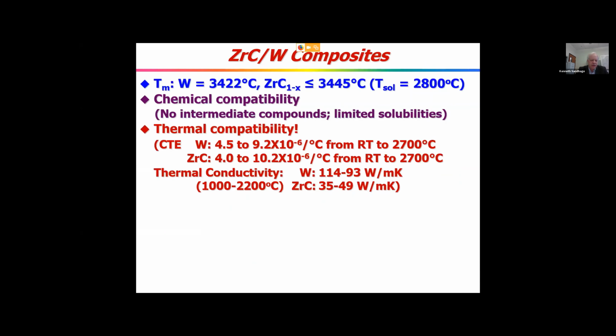What is particularly remarkable, and particularly why we picked this combination, is that they overcome an Achilles heel of ceramic-metal composites, and that's the difference in thermal expansion. The coefficients of thermal expansion between tungsten and zirconium carbide are quite close, from room temperature, 4 to 4.5 times 10 to the minus 6 per degree C, and as high as it's been measured, 2,700 C, from about 9 to 10 times 10 to the minus 6 per degree C. That is remarkably close, because in most cermets, the metal expands and contracts a lot more than the ceramic does, and that leads to internal stresses and failure. So that's not a problem we suffer from here.